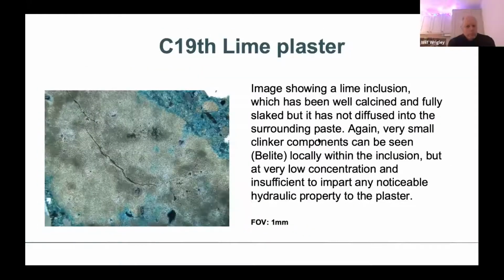And here is another image of a lime inclusion, which has been fully slaked, but it's not actually diffused into the surrounding paste. So you can see up here, this margin is quite distinct. So this is your binder here, and this is the lime inclusion. So it's not actually diffused. So this particle is likely acting as an aggregate rather than a bit of the binder. And again, there are some belite clusters.